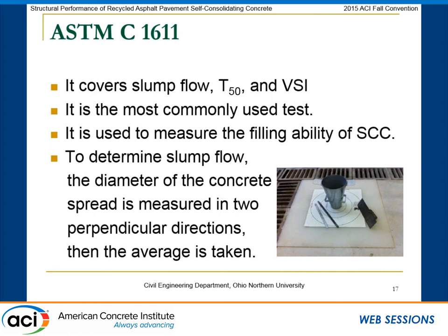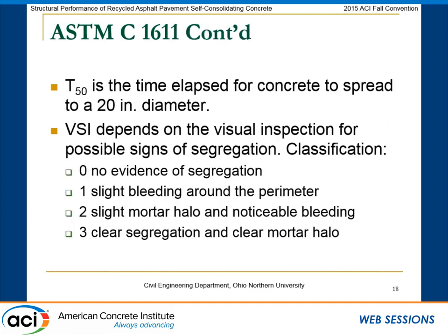So ASTM C1611, this is commonly done on the job site. So this covers slump flow, T50 and VSI. And this one measures the filling ability of the SCC. So basically you measure the diameter in two perpendicular directions and then you take the average of the concrete spread.